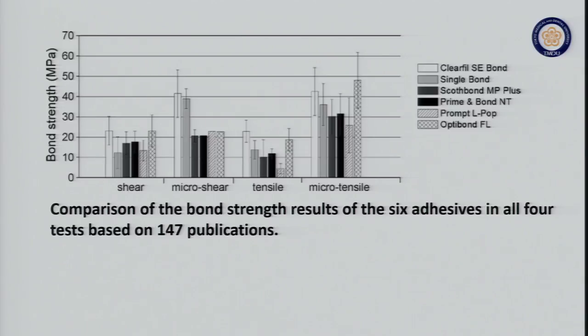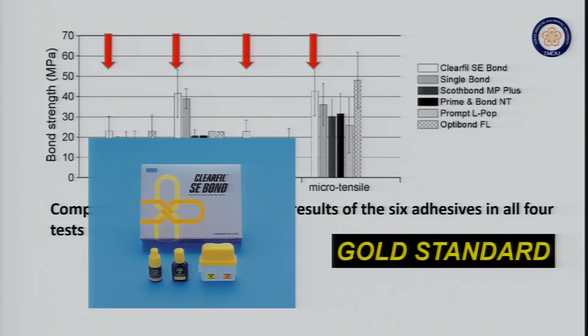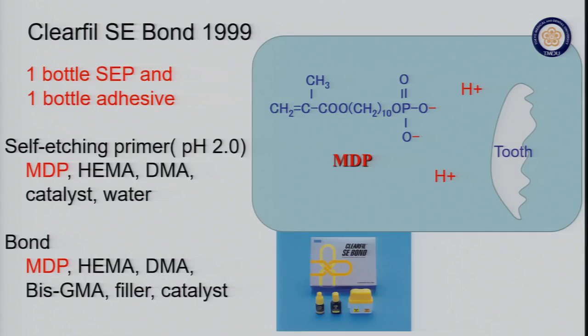In this review paper, 147 papers were reviewed, and they summarized the bond strengths according to the bond test method. This is the conventional shear bond test and the micro shear bond test with a much smaller surface area for bonding, and the conventional tensile bond test and the micro tensile bond test. In any kind of bond test, almost the highest bond strengths were obtained with Clearfil SE Bond. That is the two-step self-etching adhesive material. So that's why, from this kind of analysis, Clearfil SE Bond was recognized as the gold standard of the adhesive. So let's consider the bonding of this two-step self-etching.